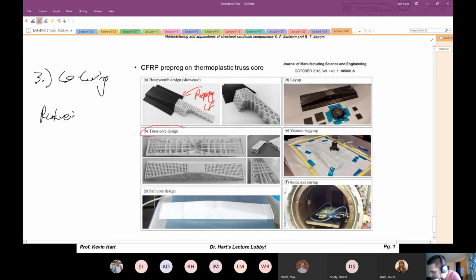All right, so here's the truss core design. You can see it in a little bit more detail. And here's the layup in actuality. So you see the carbon fiber prepreg that's laid over that thermoplastic core truss. And this here is a vacuum port. That's where you would attach the vacuum line to get into the vacuum bagging. So this is before vacuum bagging, and you can see that vacuum port there.